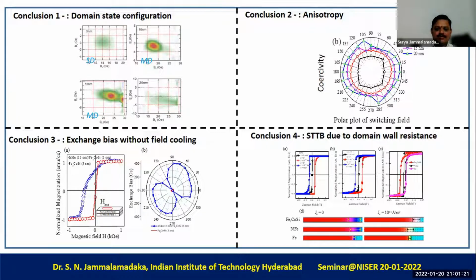In terms of the sample, we try to vary the sample plane at different angles and try to measure the coercivity and exchange bias. Right, but what sets the value zero? The zero means we have a film, and we make sure that the magnetic field is applied along the length of the film. But the question I'm really asking is, what is the origin of that anisotropy? You are depositing on an amorphous substrate, so there should really be no in-plane anisotropy, except, of course, if you have a directional deposition process. Is that what you're having?